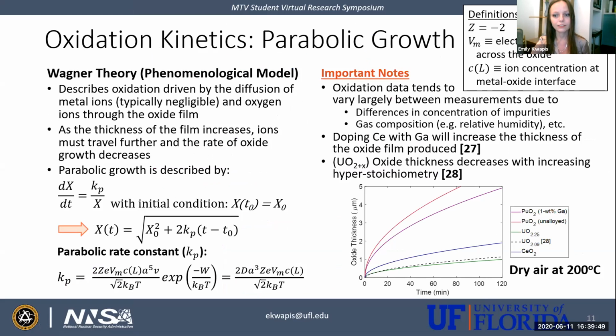And as expected from physical chemistry, you see that cerium falls between uranium and plutonium along this plot at 25 degrees Celsius in dry air. So to move on to higher temperatures where the parabolic growth model can then be taken at 200 degrees Celsius, you see the same trend between plutonium and uranium and cerium, where cerium once again falls between uranium and plutonium.